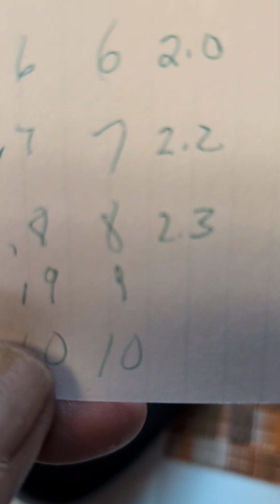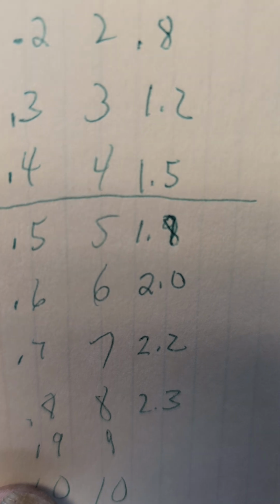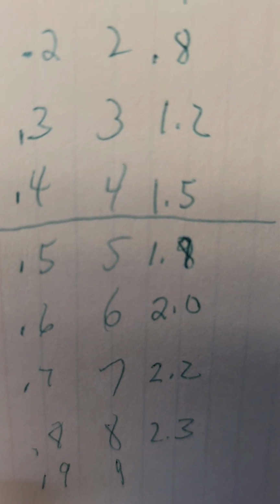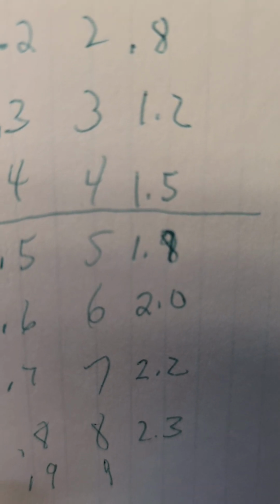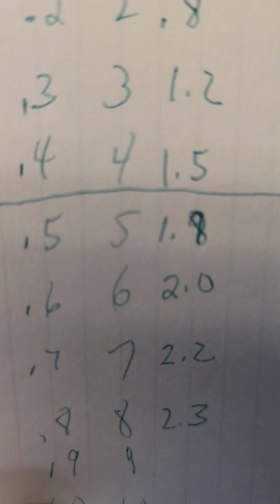6-step, 600 milliamps, 2.0 output. See the wattage going up as the current's going up. 7-step, 700 milliamps, 2.2, 2.3. Now pay attention to 4 and 5, if you will, where it goes from 1.5 watts at step 4 to 1.8 watts at step 5.